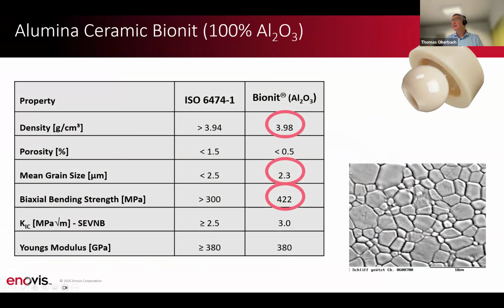We reach a density in the material which is very close to the theoretical density, we have a grain size in the material in the range of 2 microns and the biaxial bending strength of a little bit more than 400 megapascals. That means we pass all the requirements from the standard.